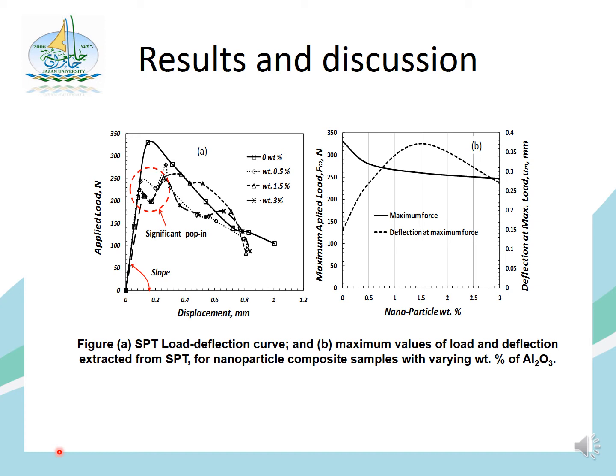And we can tell there is a significant drop for the materials with additives. The maximum is the one with no additive. Also, I'm trying to show you here how the small punch test looks. There are 4 regions: elastic region, elastic plastic region, stretching, and finally failure. And we can tell that all the samples that have any additive in the reinforced epoxy follow the same behavior, while the other one has no elastic plastic region.